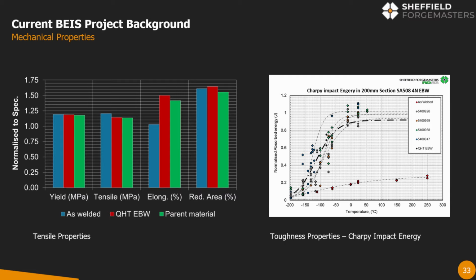So if I quickly run through the data, the blue bar graph is showing tensile strength. Blue shows the as-welded condition, so straight out of electron beam welding. Green shows the parent material, so what the forging is typically made of, our typical product, what we would send out every day. And the red is the quality heat treated, so the heat treated electron beam weld. From the strength, we can basically say it's equivalent to parent, if not ever so slightly better.